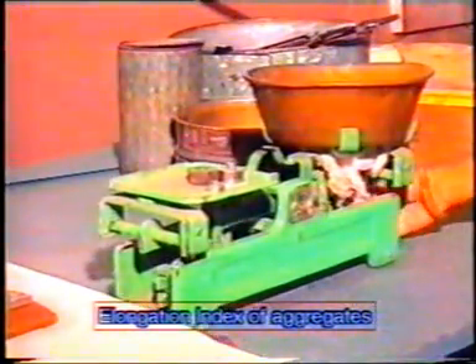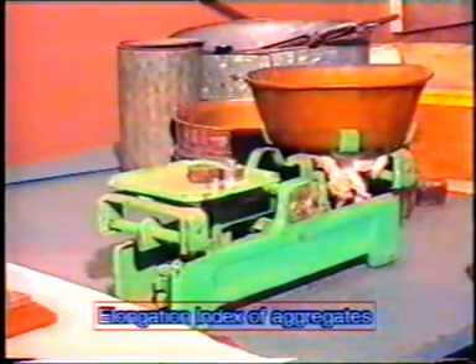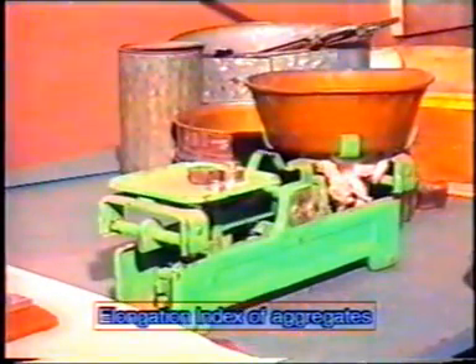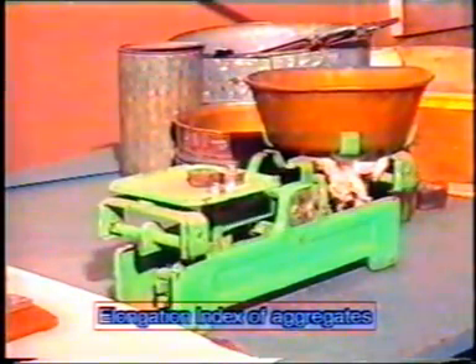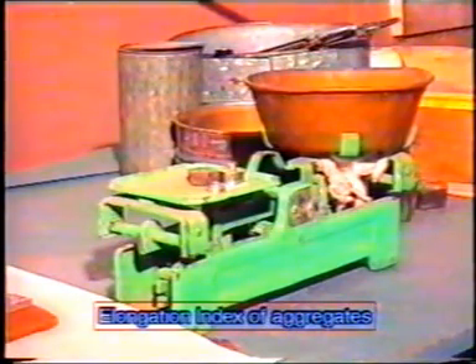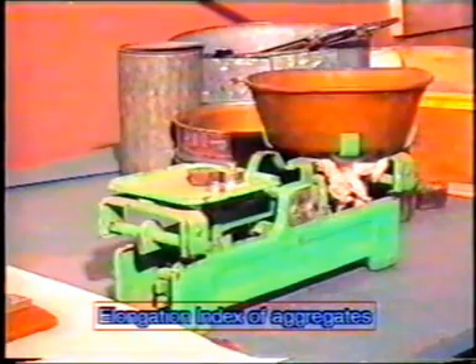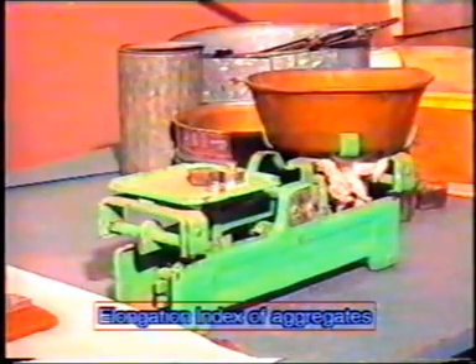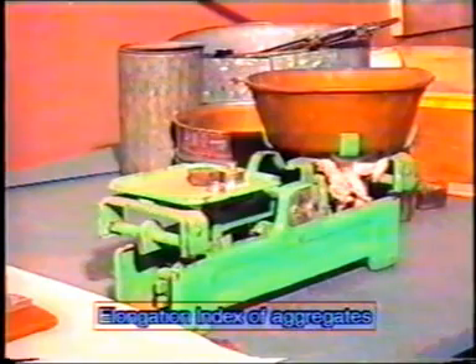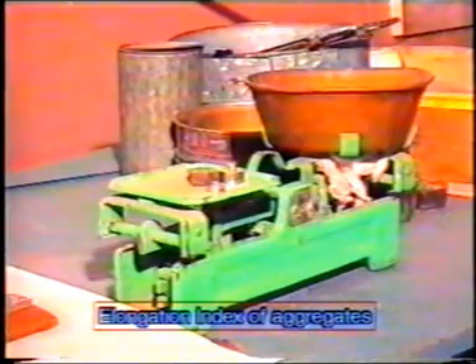The sum of weight of all fractions in which pieces pass through the corresponding slots and the total weight of all fractions is to be calculated. The elongation index may be reported as the weight not passing lengthwise divided by the total weight of the sample into 100.